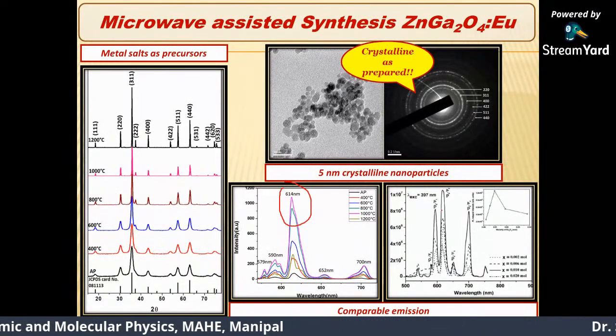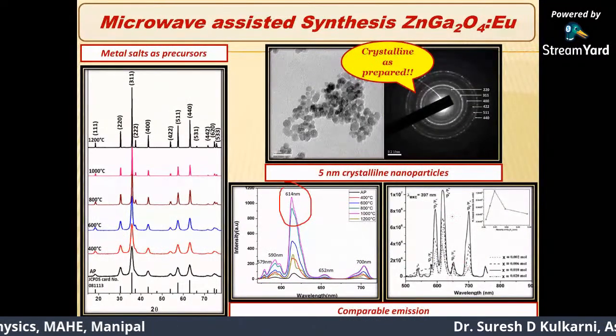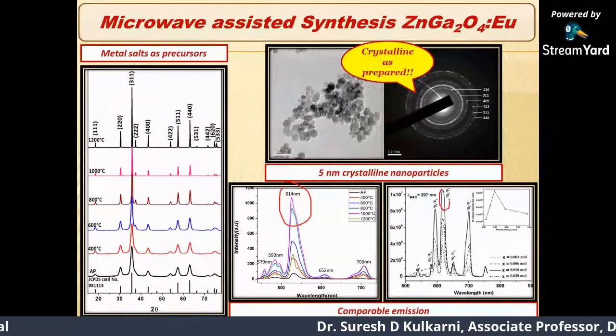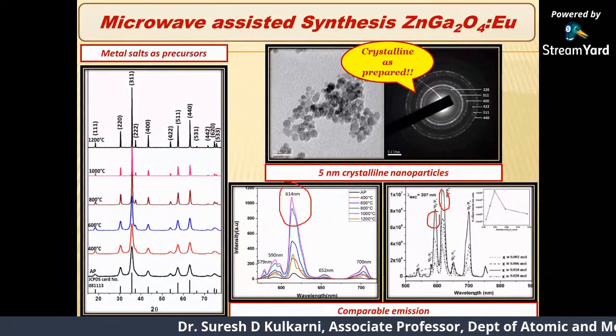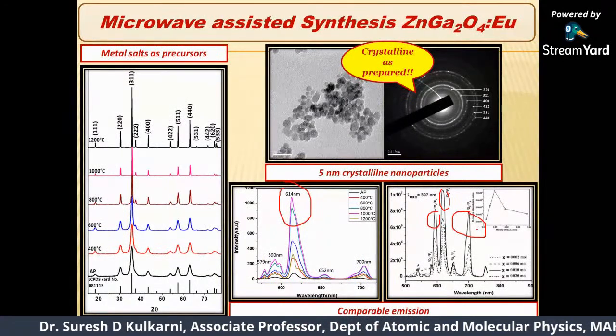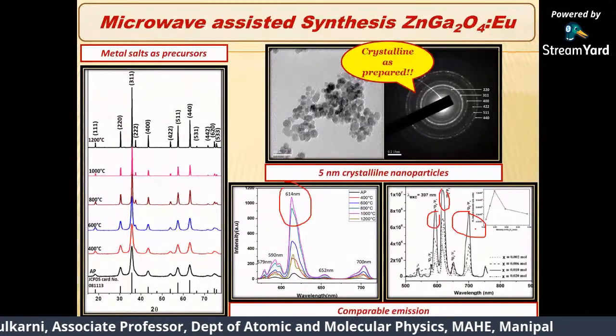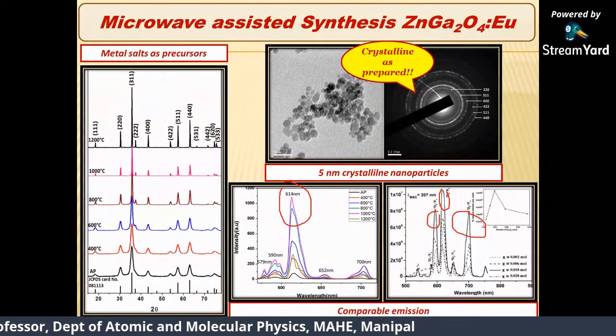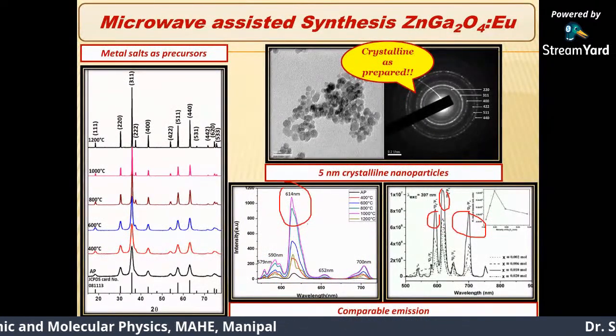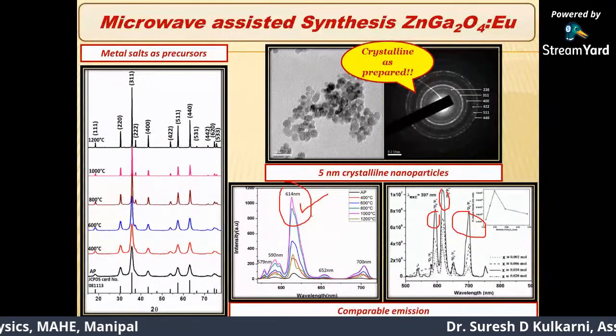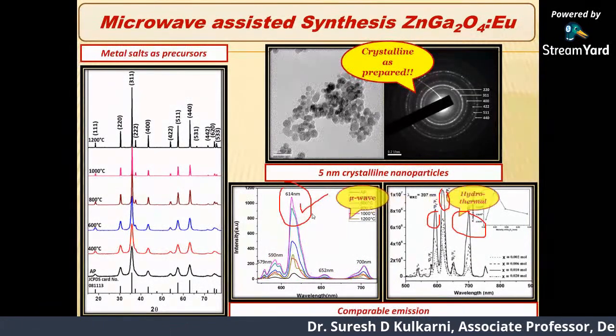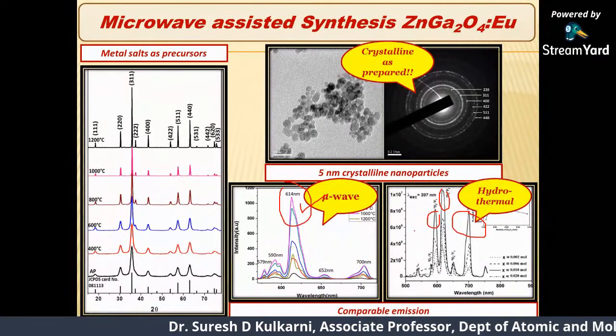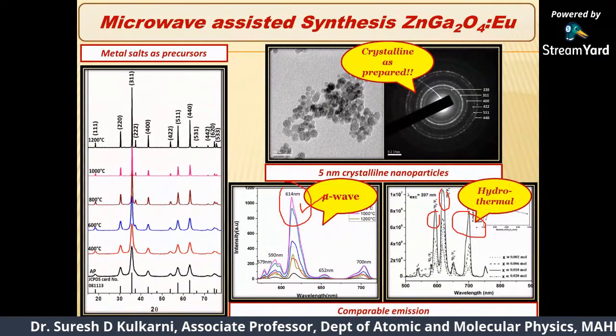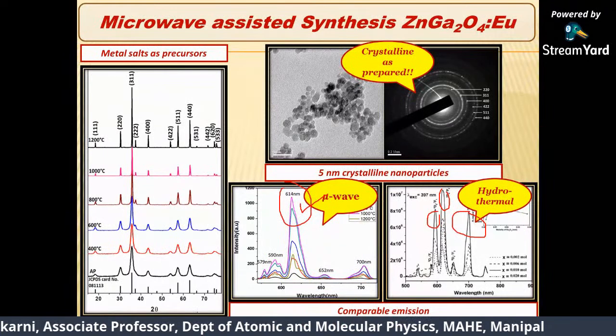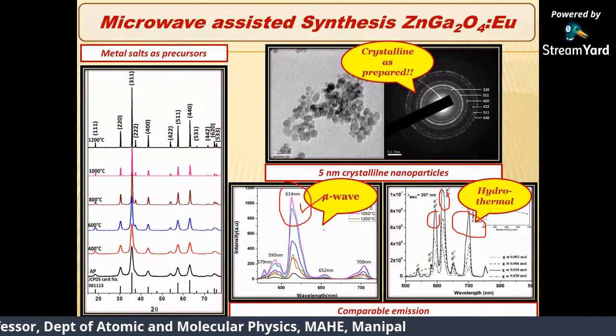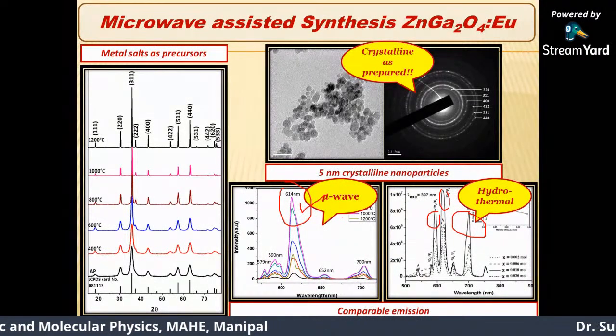If you compare this with some of the literature, this is supposed to be the red emission, but all other emissions are dominant in the earlier case. These are unwanted emissions, especially considering the television industry. You can see here our material shows predominantly 614 nanometer emission. What we are showing here is a hydrothermal approach, synthesized as in the literature I have mentioned below, whereas our sample prepared using microwave is giving good quality emission.